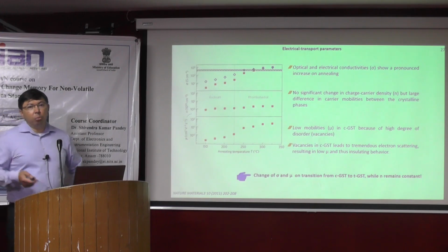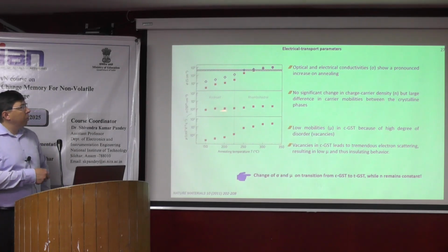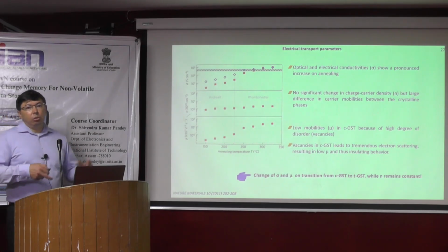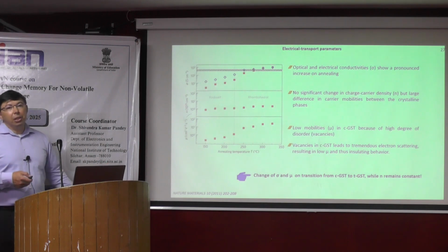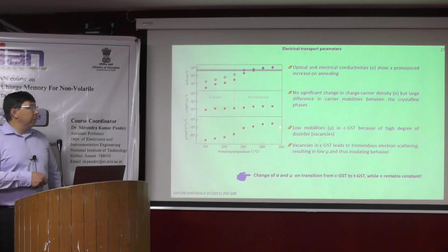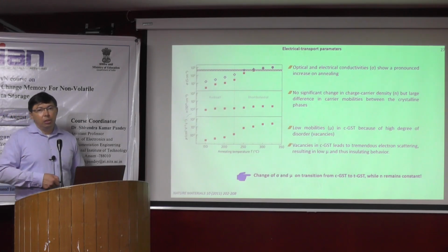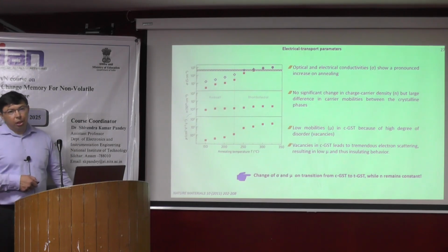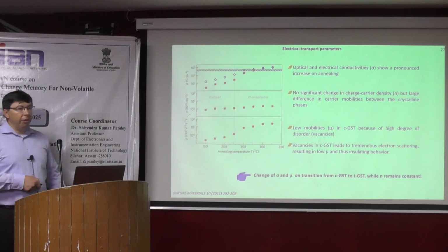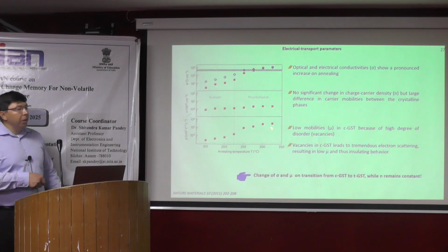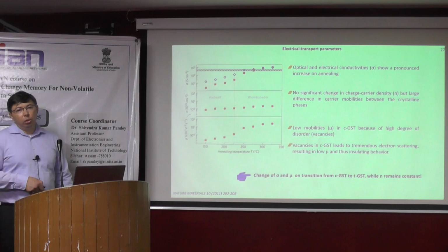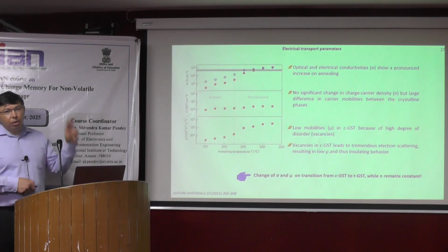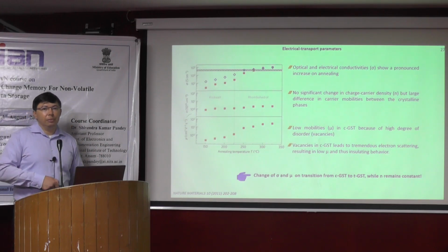So it has higher mobility, but the same number of charge carriers. So it is only the mobility that changes and that brings the metallic behavior. Actually, both phases are semiconductors, non-degenerate semiconductors, especially in this phase. But the metallic behavior is really because of the higher mobility of carriers compared to the non-metallic, insulator-like phase. All right. Thank you.